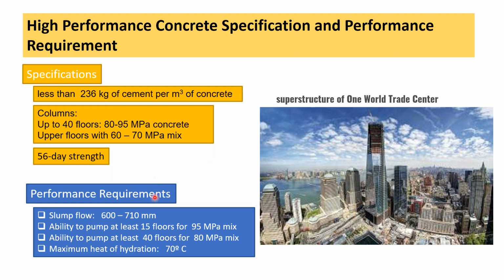Now, there were also performance requirements that were put in place. The concrete mixture that is produced had to have the ability to be pumped for at least 15 floors if it's a 95 megapascal mix. And if it's an 80 megapascal mix, it should be pumpable for 40 floors. This is a performance requirement that is specified. The maximum heat of hydration was specified at 70 degrees Celsius. And of course, there are other performance requirements in terms of measured performance in a specific test like the RCPT, rapid chloride penetration test. So these are all specified.